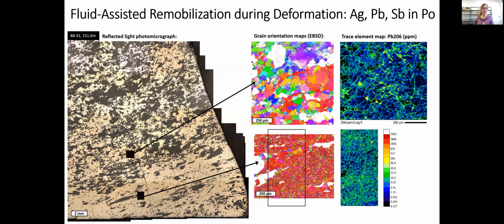And this suggests that these elements, lead, silver, and antimony, are really mobile during deformation. They're moving along the grain boundaries, moving along any other boundaries they can find, and this is probably with the help of a fluid.